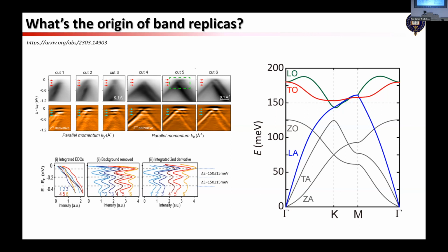And the phonon, we got out of this phonon spectra, but to our very disappointment, at the gamma point there's no phonon mode that coincides with this 150 meV. Although the energy resolution is not so great, it shouldn't be so large as to miss it.